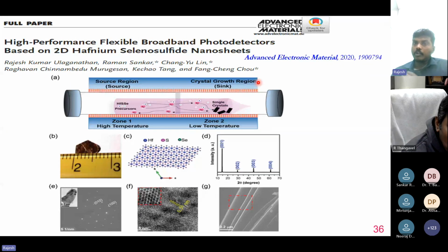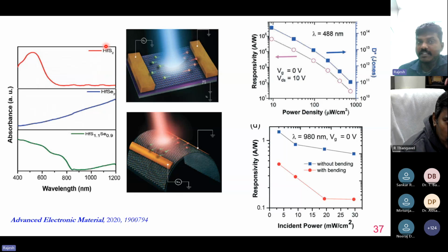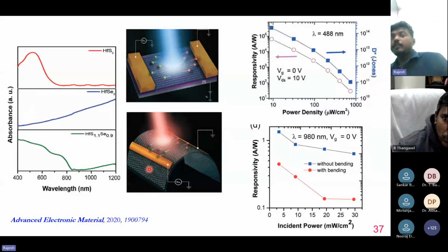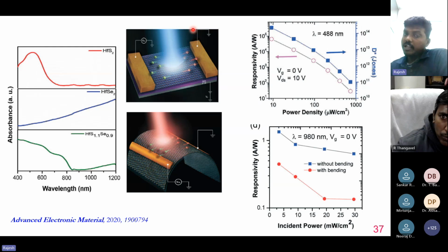In another work, we grew hafnium sulfoselenide nanosheets by the CVT technique and demonstrated its high single crystalline nature with the help of XRD as well as the SAD pattern, and demonstrated that this hafnium sulfoselenide has broadband detectivity. Hafnium disulfide has absorbance only in the visible region. In the case of hafnium diselenide, it has absorbance in the near infrared region. So by having 1:1 hafnium sulfoselenide, we are able to expand the absorbance from visible to near infrared. In this way, we prove that hafnium sulfoselenide can act as both a visible photodetector as well as an infrared photodetector.